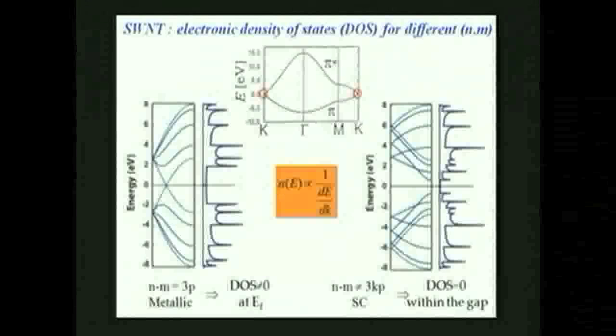So you will find two particular results. First, each time you have a flat band, which is a zero derivative in the dispersion curves, and this happens often at the edge of the Brillouin zone, you see that here you have a zero curvature, a zero derivative. Each time you have that, if you integrate over the wave vector, you will find a singularity in the density of states.